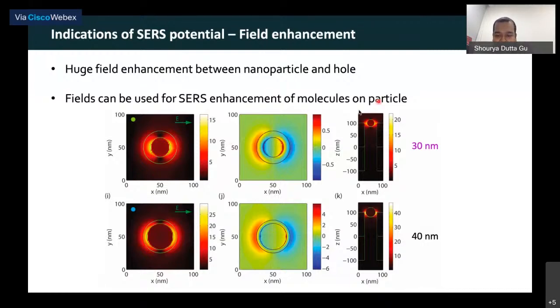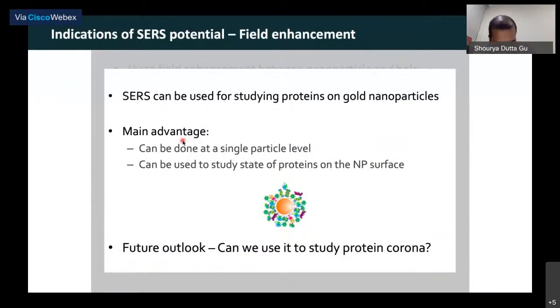Now this is the cross-section view, and there are two different particle sizes. What we see is a high field between the particle's wall and the wall of the cylindrical hole that we have. If we place molecules here, the Raman will be significantly enhanced, by a factor of 15 to the power 4. This is what we plan to use for doing SERS using these structures. So the idea here is, I would like to conclude the first part.